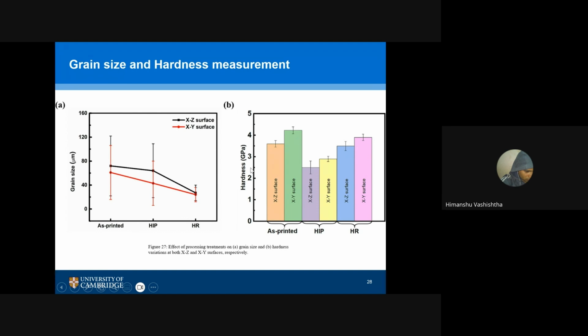Now we have measured the hardness. One would claim the standard thumb rule is, if the grain size is low, the hardness or mechanical properties shall be pretty good. However, in this case, we are getting very high hardness for the as-printed case. What can be the reason? Can you imagine in your mind without me telling you? For the as-printed case we're getting pretty high hardness. However, for hot rolling, where the grain size is the lowest, it shall be the highest, right? But it's not.